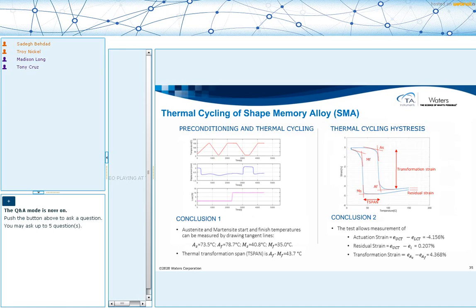Here's what the data looks like. Let's just start on the left, looking at the three graphs that show you the changes in temperature, displacement, and load with time. So starting from the top, looking at the temperature changes with time. So this is a preconditioning. We go up, hold for a few minutes, go back down, cooling, and then we go up again. This is the first 2000 seconds of your experiment. So we are just preconditioning, no load. If you look at the third graph from the top showing load versus time, you see that there is zero load. Then we hold that temperature in the upper end at 150 C.